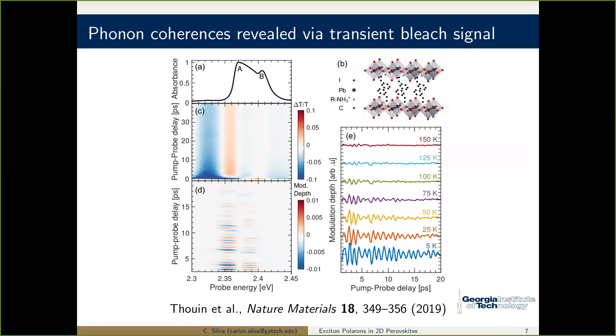We do transient absorption in a configuration that allows us to pull out impulsive stimulated Raman components. So here what we are going to do in this data is pump-probe transient absorption, pumping the band-to-band transition. So this is a pretty high energy, injecting photocarriers in this system. This is all done at 5 K at the moment for the data on the left. Here we pump, we inject photocarriers, but we probe in the exciton bleach region. And for no fancy reasons, let's call this exciton A and exciton B.